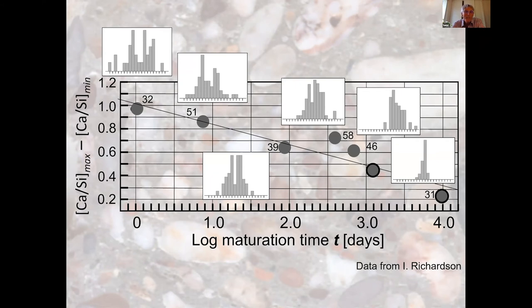Now, what is stranger is that if you look at the local distribution of calcium to silicon ratio in a cement paste, using data from Jan Richardson, for instance, who did extensive characterization in this field, what you see is that young pastes have a very broad distribution of calcium to silicon ratio. Always the same average, but the distribution is very broad. And as time goes on, the calcium to silicon ratio gets a narrower and narrower distribution. And this follows a logarithmic scale.